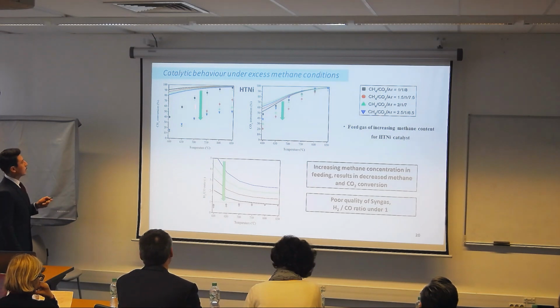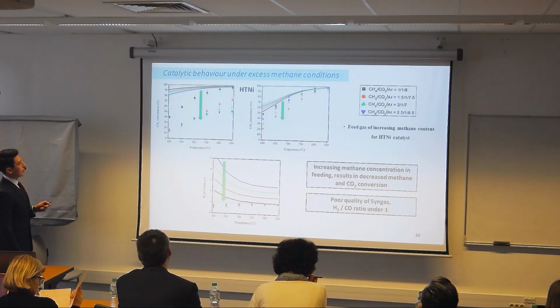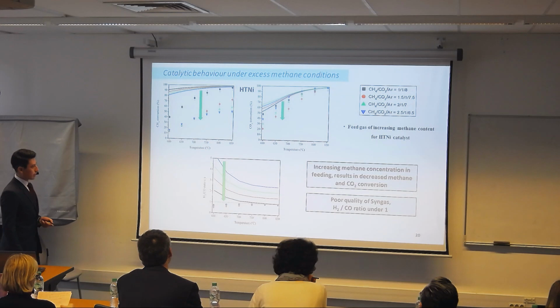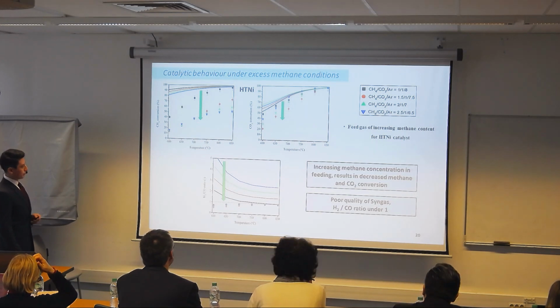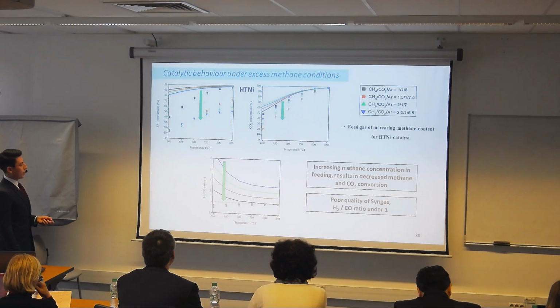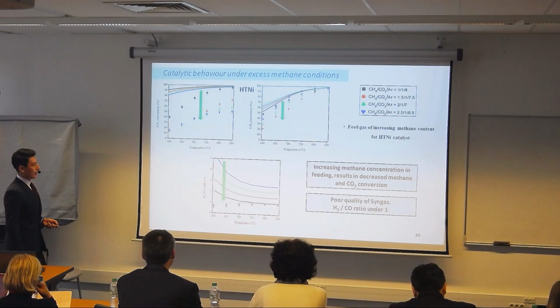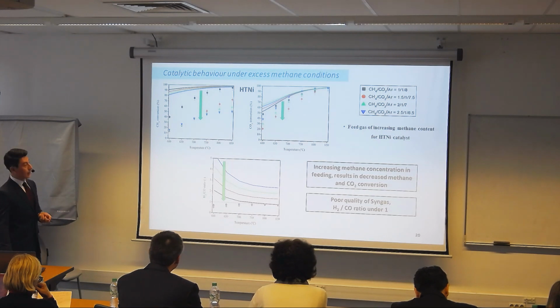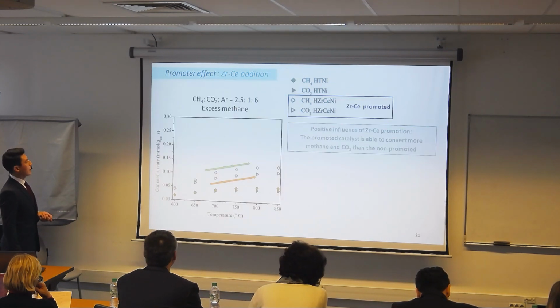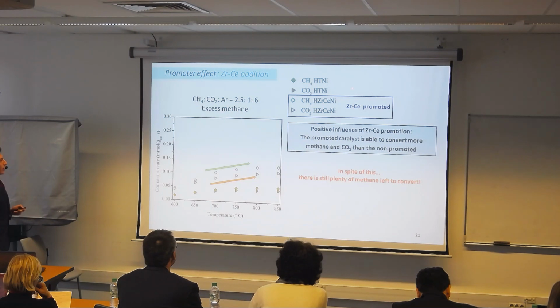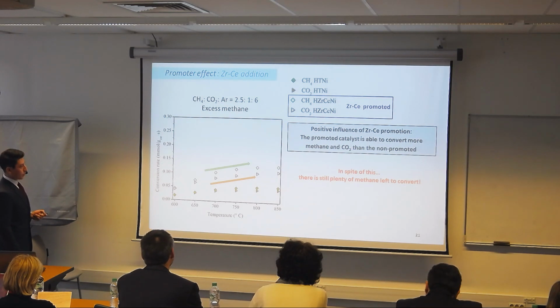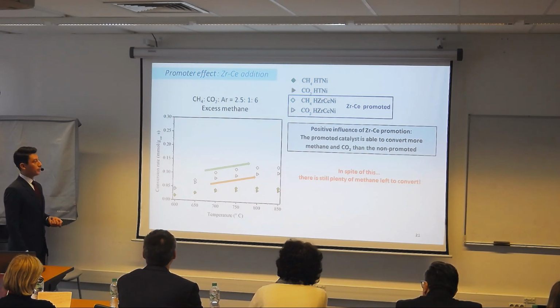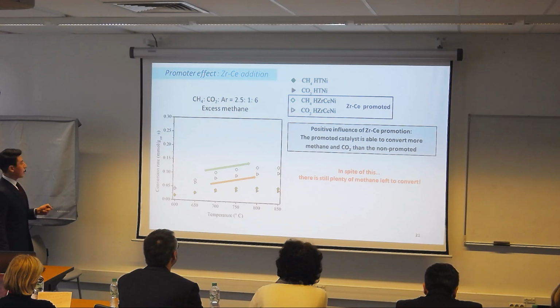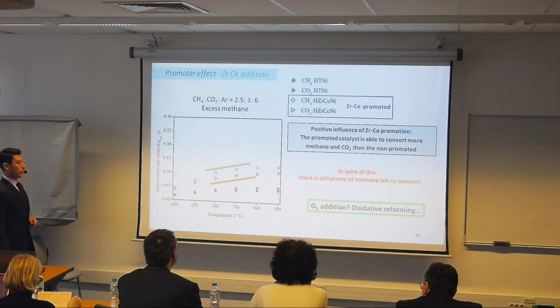We clearly see here that as we increase the concentration of methane, all the values are getting farther from the thermodynamic forecast for methane and CO2. We also have a poor quality of syngas, and so after this we wanted to test the promoted one. When we introduce zirconia and cerium, we have an increase in the concentration, so we have a positive influence of this promotion. However, we still have a lot of methane not converted.